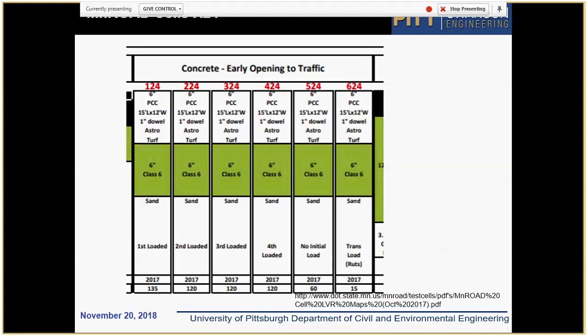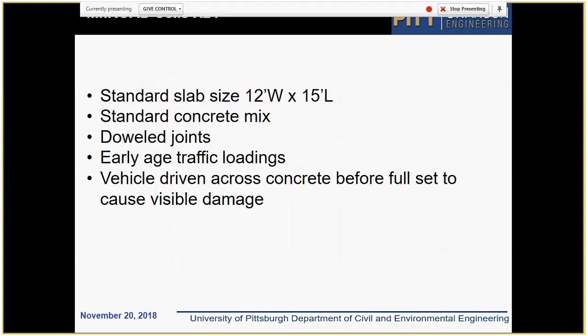So as Ben mentioned, at MnROAD, cell 24 was reconstructed, and several test sections were created. All of them have the same thickness, all of them have the same dowel design, like 1-inch dowels. They're built on a 6-inch thick granular base and on sand subgrade. But they differ in the way they were loaded. Before I move on, all of them have standard slab size: 12 feet standard width and 15 feet joint spacing.